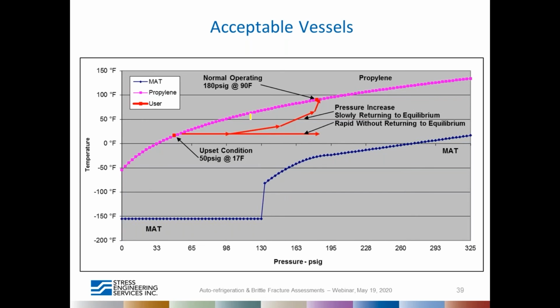In this case, the medium is propylene. Once again, the operating pressure is 180 psi and the temperature is 90 Fahrenheit. And the MAT curve is a little different than the previous one, so this is a different vessel. Once again, if you're operating at this pressure and temperature, you're safe. And when you go along the flash curve and then you come back and you want to restart, once again, you're safe if it is rapid without returning to equilibrium. Our typical process restarts would involve slowly returning to equilibrium. And the process should place controls to consider these upset conditions, because if you go below 17 degrees Fahrenheit on this curve, then you would intersect this MAT curve, which will put this vessel at risk.